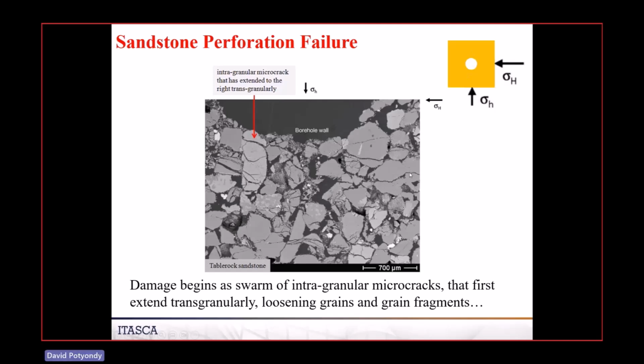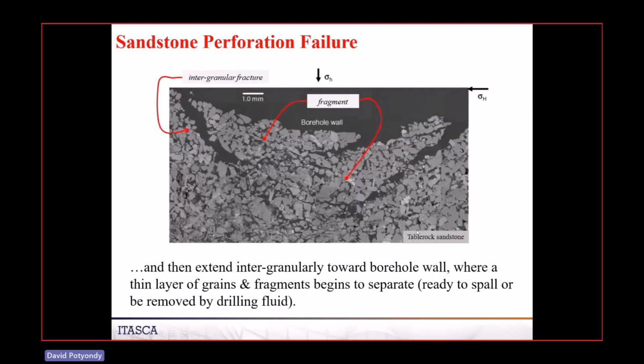And the damage, if you look closely, notice the length scale, 700 microns. This was work done by Professor Haimson at University of Wisconsin-Madison some years ago. So here's Tablerock sandstone. And notice what you're getting is this swarm of broken material very close to the borehole wall. And that's consisting of both breakages along the grain boundaries and the grains themselves. You can see clearly the grains are also splitting in this system.